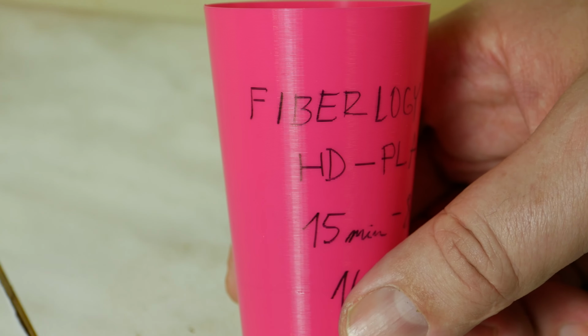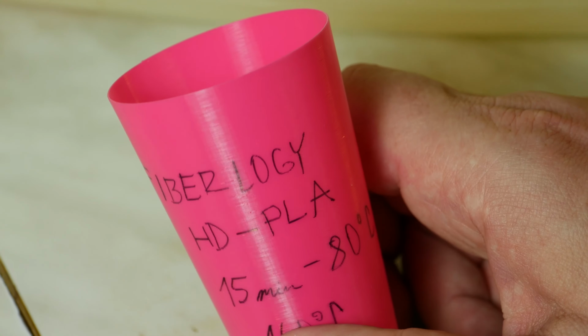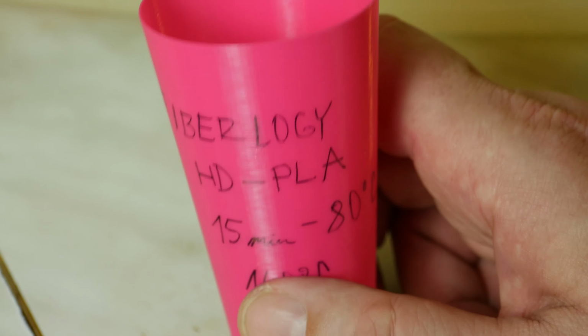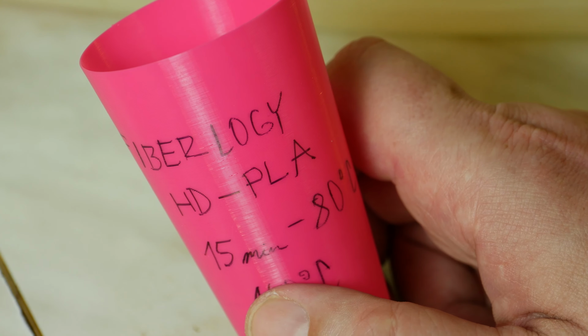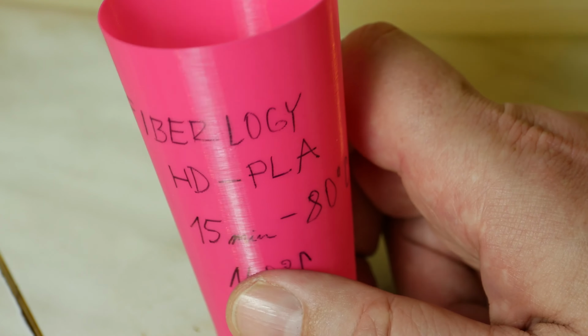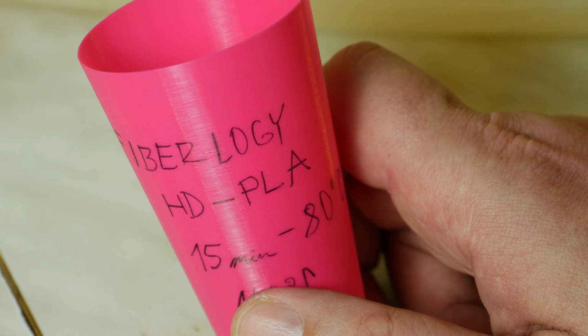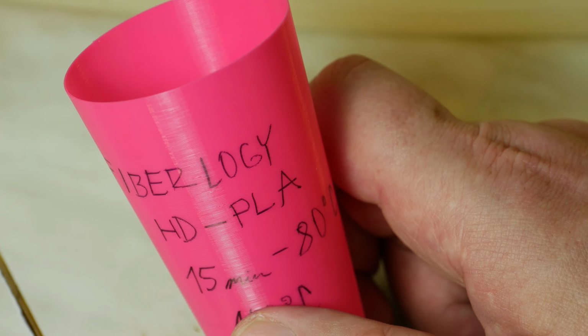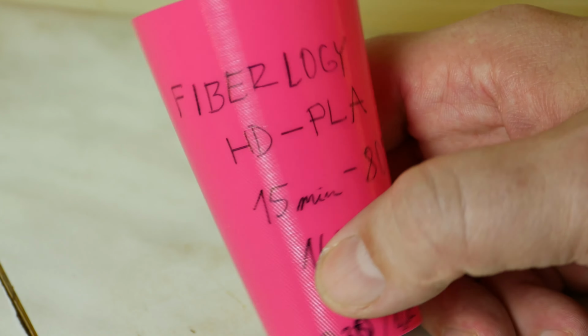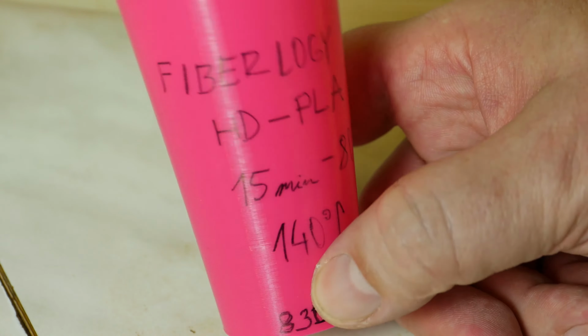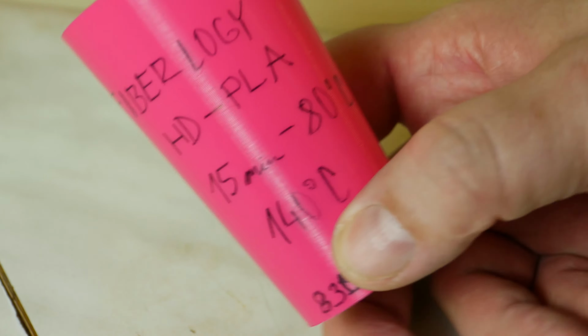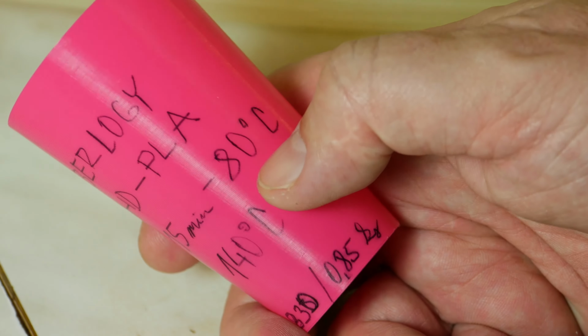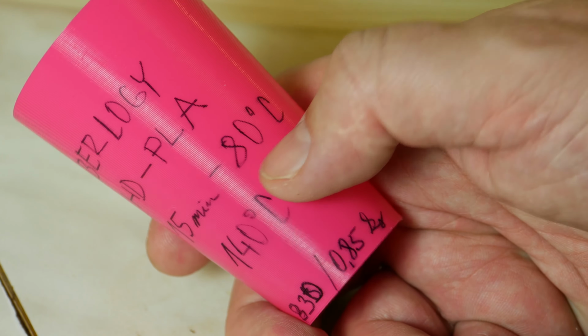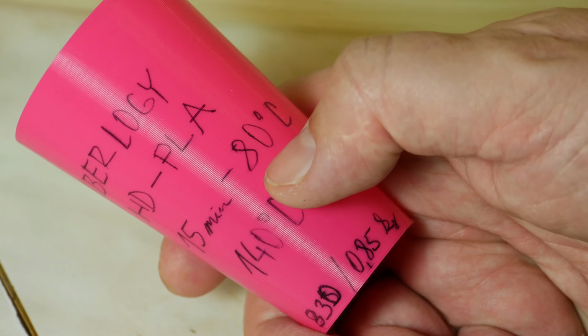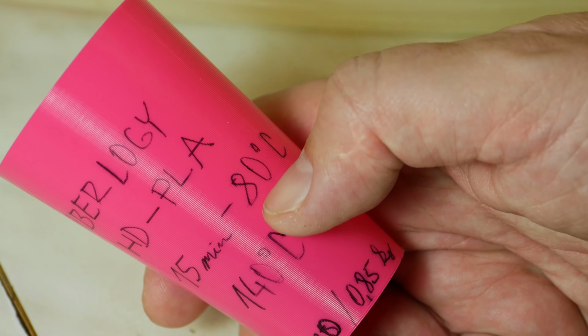Annealing, what does it mean? You just print your part. During print, this is just standard PLA, no problem during print. Hot end temperature, hotbed temperature, everything is just the same as normal PLA without any problems. And after print, best solution is directly on a mirror or on glass. If you use this on a hotbed, you will put it with supports and everything. If you have supports, you will put it in the oven, and you will anneal it in the oven for 15 minutes at 80 degrees Celsius. This temperature must be exact, maybe 5 degrees minus or 5 degrees plus.